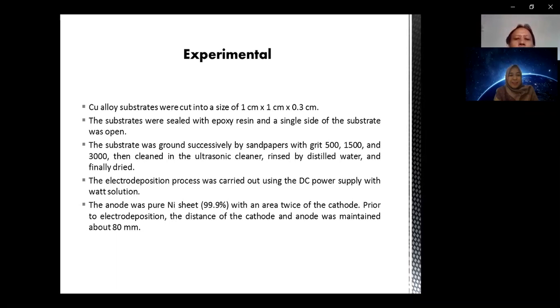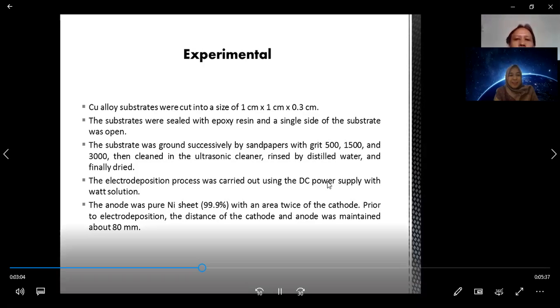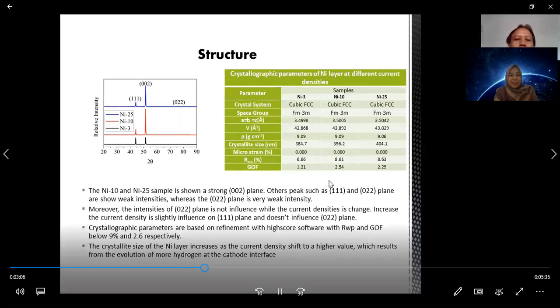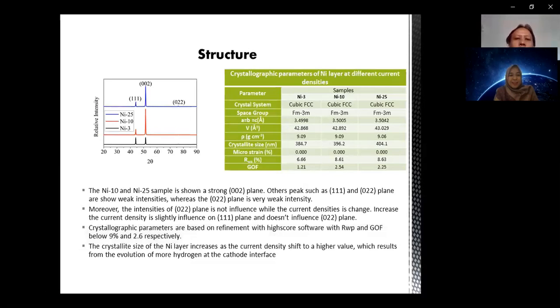The electrodeposition process was carried out using a DC power supply with Watts solution. The anode is a pure nickel sheet, and the distance between cathode and anode is maintained at about 80 millimeters. In the structure, we can see three major peaks: 111, 002, and 022.